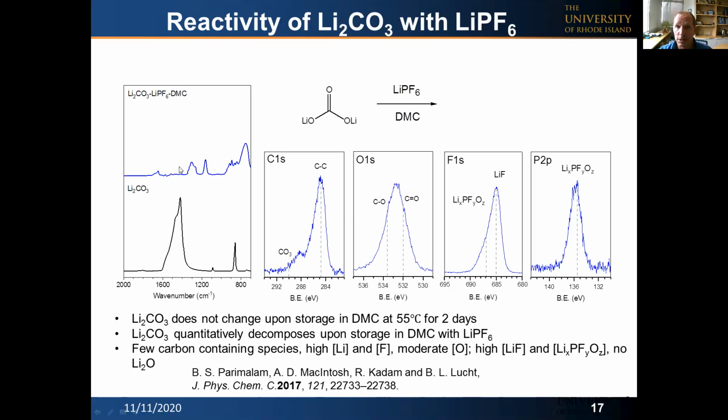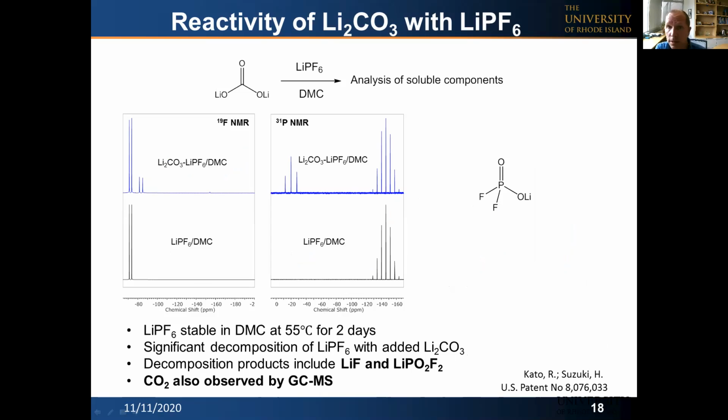If we look at the XPS spectra of this residual material after the decomposition, what we observe is there's low concentrations of carbon and a little bit of oxygen, but very high concentrations of lithium fluoride with low concentrations of lithium fluorophosphate. If we go back and look at the solution, the dimethyl carbonate solution by NMR spectroscopy, what we observe is a single new peak in the NMR spectra. We have the LiPF6 doublet and septet, and now we have a triplet and a doublet, which is consistent with the presence of this lithium difluorophosphate species in a very clean reaction.